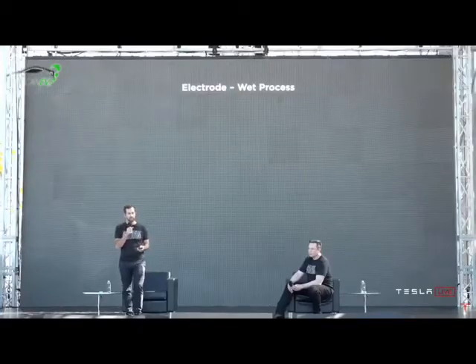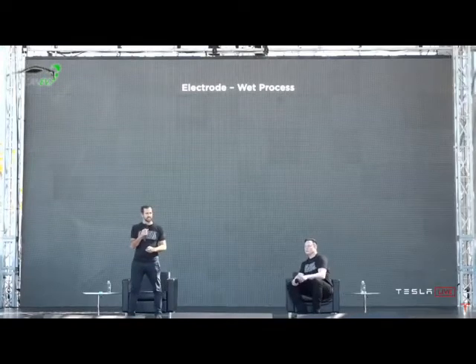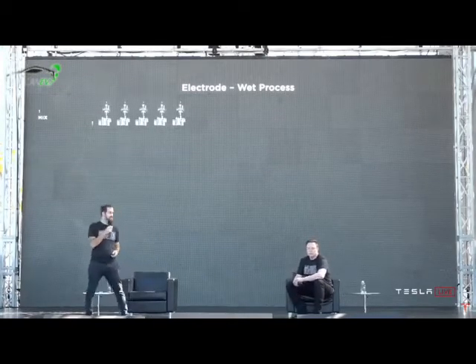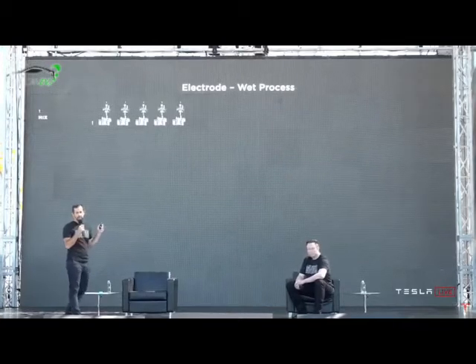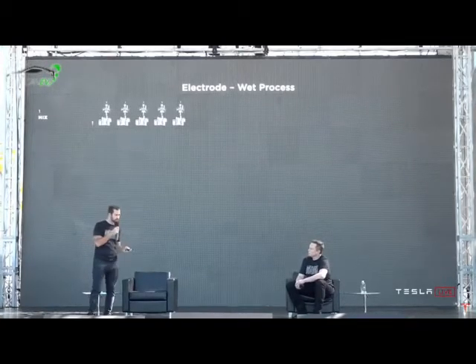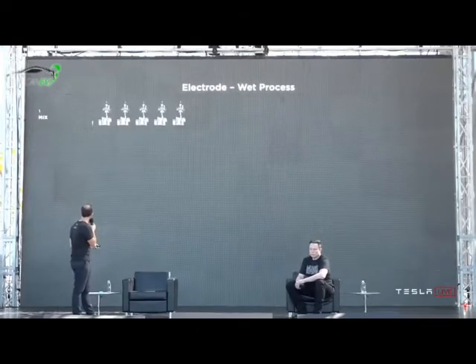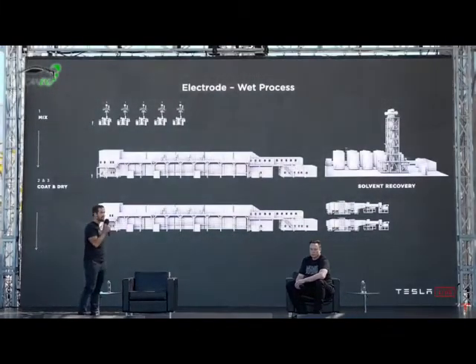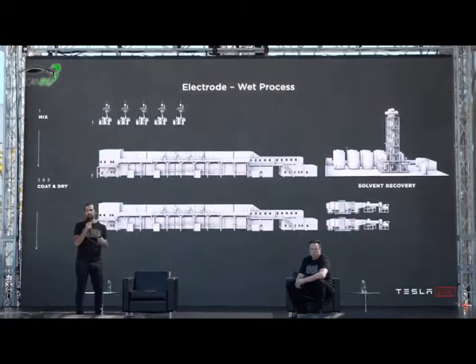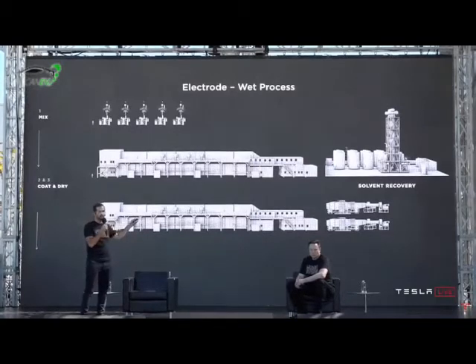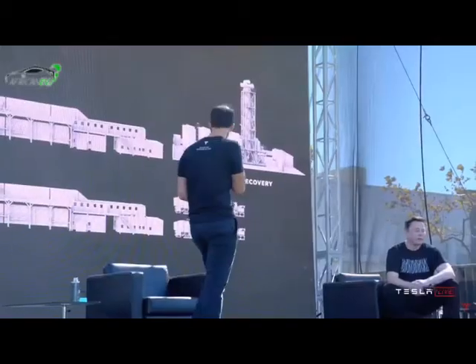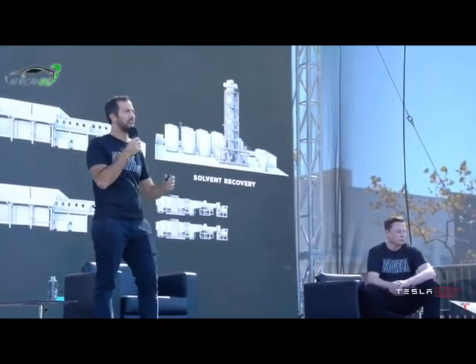One of the most important processes is where it all begins, the wet process of the electrode coating. Just to give you all a sense of scale, I'm going to walk through what's in that wet process. You've got mixing, where the powders are mixed with either water or a solvent for the cathode. That mix then goes into a large coat and dry oven where the slurry is coated onto the foil. Huge ovens, tens of meters long, dried, and that solvent then has to be recovered. You can see the solvent recovery system. And then finally, the coated foil is compressed to the final density.